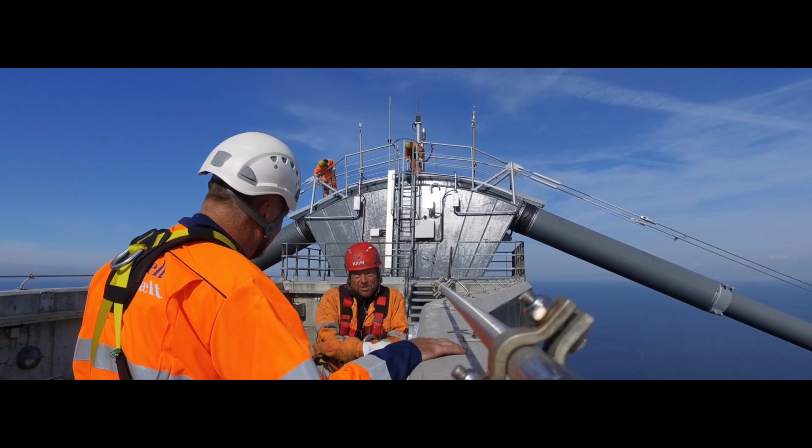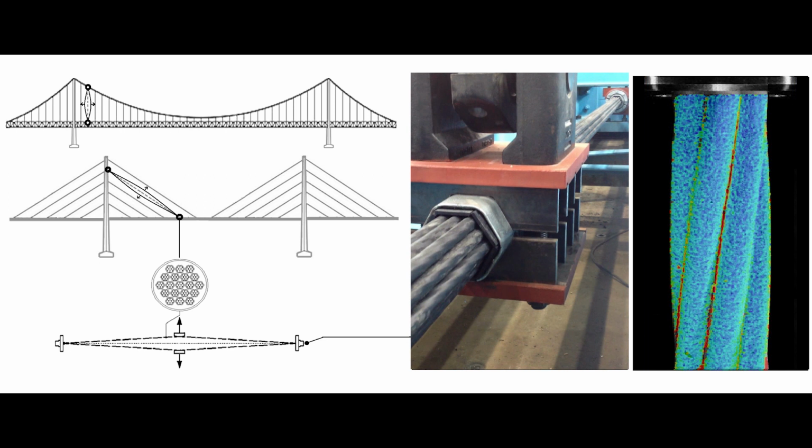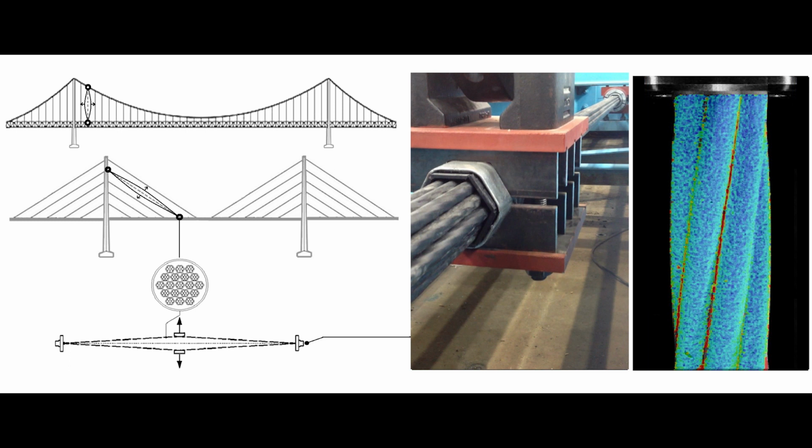Atkins have a unique expertise within cable fatigue management. Atkins research work developed an innovative method based on DIC that relates amplitude of cable vibration to friction between steel wires and eventually to fatigue life. The outcome of research influenced international design recommendations and can be used for better estimation of fatigue life and management of cable-supported structures.